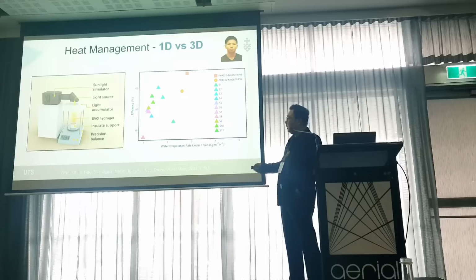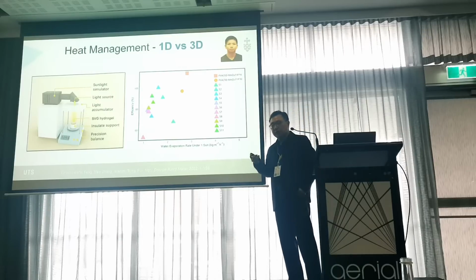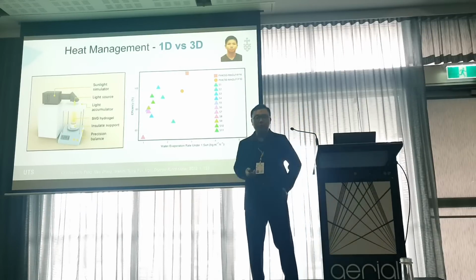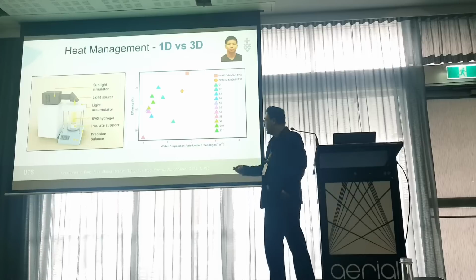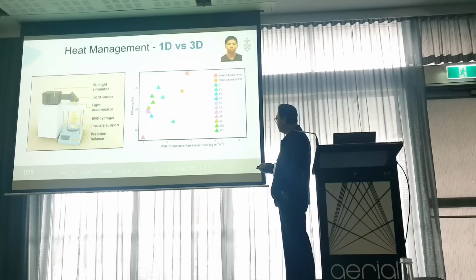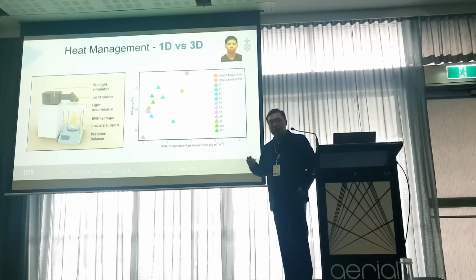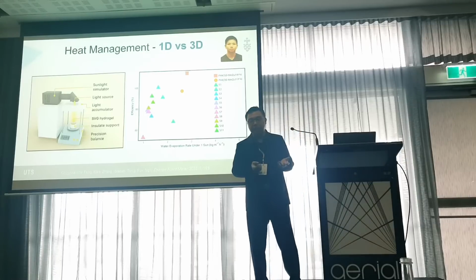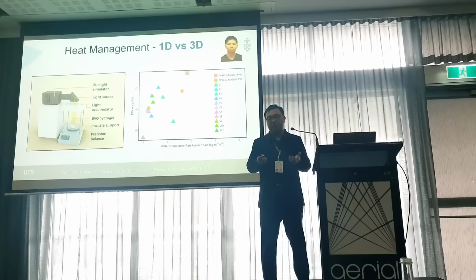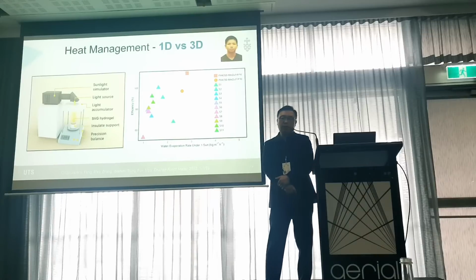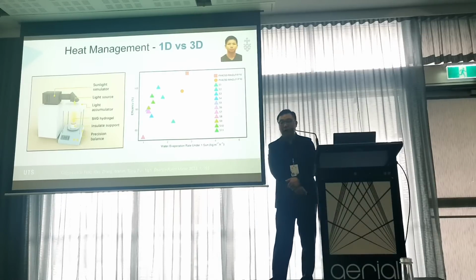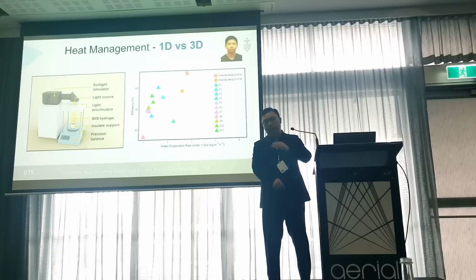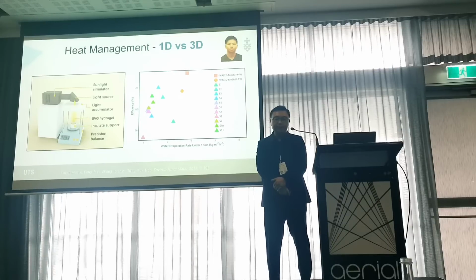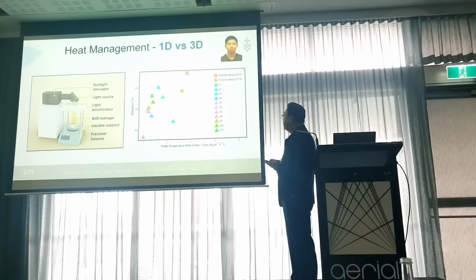And then we use this homemade setup to test the solar vapor generation efficiency, or the water evaporation rate, of our hydrogel materials. And the results are summarized in this table. As you can see, the PVA hydrogels with 1D nanorods show the highest SVG performance compared to all the semiconductor-based hydrogel systems. They achieve about 2.8 kilograms per square meter per hour, as well as very high solar to vapor efficiency. And this performance is definitely better than the 3D nanoparticle one.